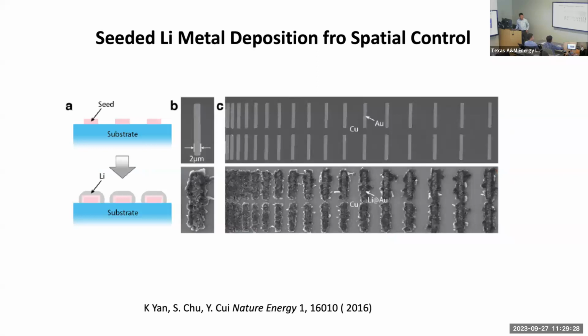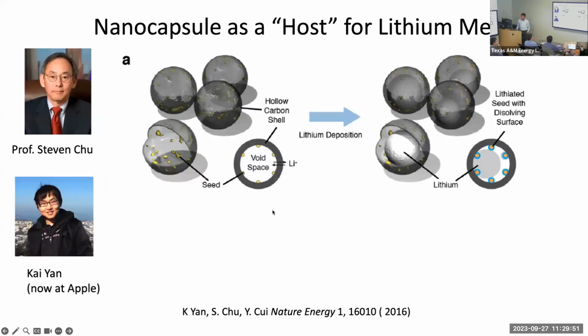Based on this, we now can design on a copper substrate. We pattern this gold line, and then after deposition, you see lithium only likes to deposit onto where the gold is. They want to grow right there. So this is the first time we can spatially control, during battery charging, where lithium will go. And based on this idea, we actually designed this hollow carbon with the gold as the seed, and built the electrode. Now lithium metal will deposit inside instead of outside.